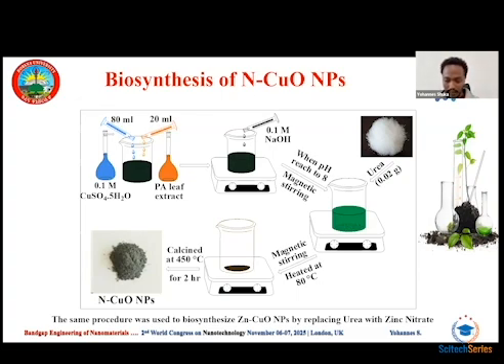That means stirring the solution on the magnetic stirrer at 80 degrees Celsius. After that, the precipitate was transferred to a furnace for calcination at 450 degrees Celsius. And finally, we obtain nitrogen-doped copper oxide nanoparticles. The same experimental procedure was used to biosynthesize zinc-doped copper oxide nanoparticles by replacing urea with zinc nitrate, which is the source of zinc.